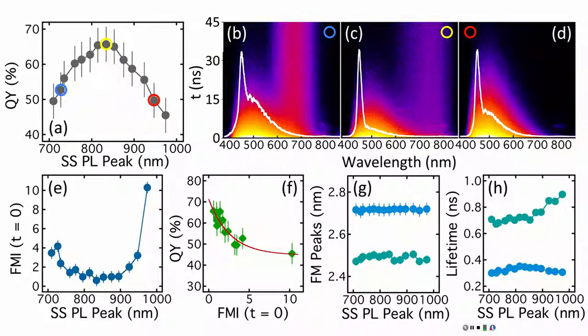But it's still possible to have hydrogen on the surface? Oh yes, there's most definitely hydrogen. That's what the plasma does. It passivates it initially with hydrogen, and then we go in and put the hydrocarbon chain on instead.